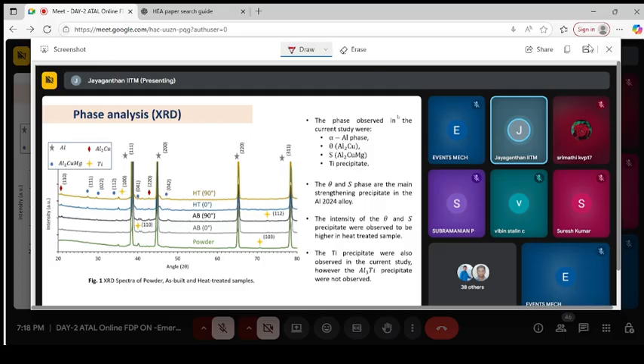Precipitate role was not accounted properly. Precipitate was not properly sized. Rather than having spherical precipitate, you have needle-like precipitate. If you have needle-like precipitate, that is going to act as a stress raiser, and a stress raiser is going to be detrimental. For example, if you have a crack with needle precipitate, that means stress will accumulate at a very rapid rate. So we need to prevent that. We need to control the size and shape of the precipitate, and not only precipitate, as we discussed, the overall grain size of the material being formed.